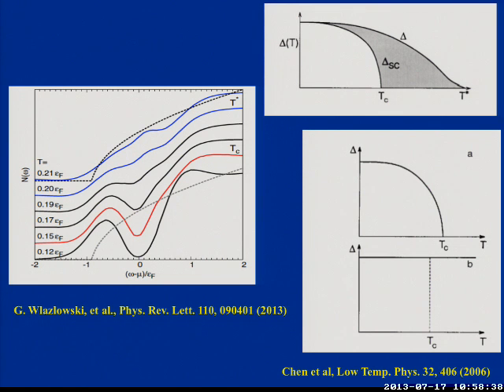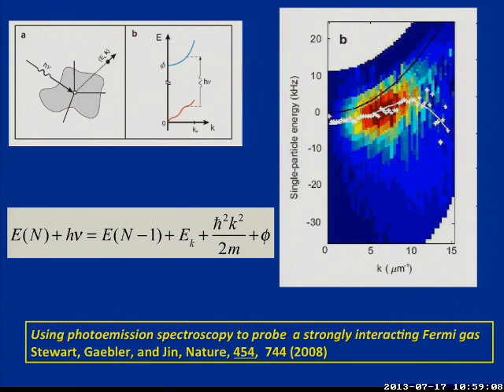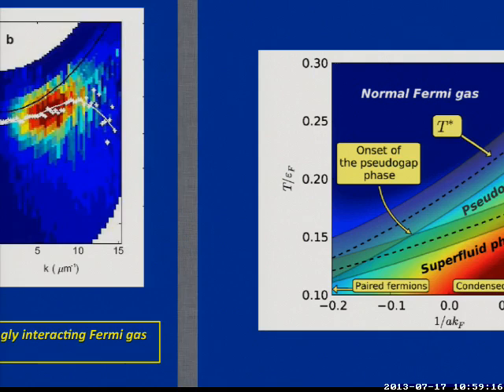So why this difference? Unlike a BCS superfluid, when you reach the critical temperature, you don't destroy the Cooper pairs. In this superfluid, not all the molecules condense into zero momentum states. You have a significant number above. So you simply have a gas of these molecules still existing. Some of them are broken, but you still have a lot. And this shows in the gap. You didn't break them all. Okay. There are experiments, whose quality, in my opinion, is not very good, which confirm the existence of this pseudo gap. So I'm going to skip that.